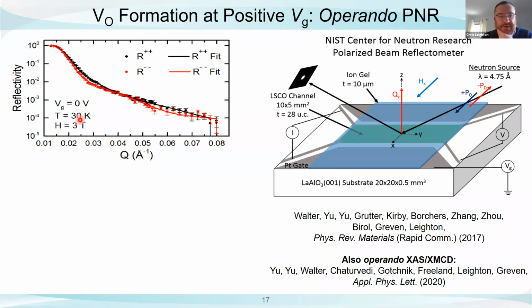This is at low temperatures in a saturating field here at 0 volts. And we plot 2 channels in this graph, what we call the plus plus and the minus minus, meaning we're bringing in parallel neutrons and counting parallel neutrons out, or bringing in anti-parallel neutrons and counting anti-parallel neutrons out. And there's a difference between the plus plus and the minus minus, and it oscillates.